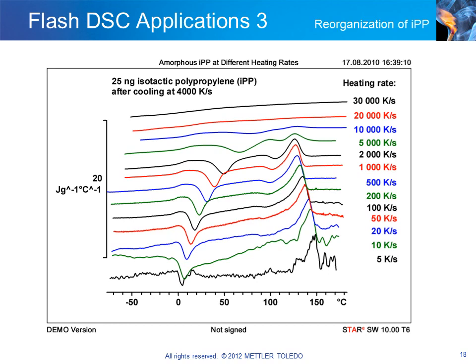This next example also shows the effect of reorganization on heating. Isotactic polypropylene was cooled very rapidly from the melt at 4000 degrees per second to obtain an amorphous sample. The sample was then heated at heating rates between 5 and 30,000 degrees per second. To facilitate comparison, the curves are displayed in heat capacity units and are also normalized with respect to sample mass and heating rate. In this heat capacity presentation, exothermic processes are shown in a downward direction. The glass transition appears at about 0 degrees Celsius, followed by the exothermic peak due to cold crystallization. The melting peak is between 130 and 150 degrees.